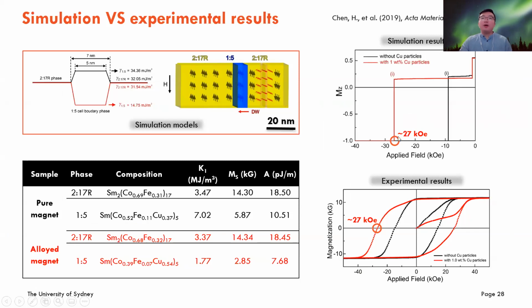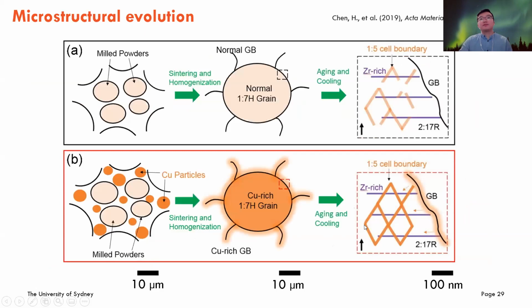For the newly copper alloyed magnets, the coercivity can reach around 27 kilo-oersted, which is almost double that of the pure one, and is quite consistent with our experimental results here, 27 kilo-oersted for the copper alloyed magnet. And then we compare the different microstructures we found. Firstly, the 1:5 cell boundary phase becomes more continuous, but also the copper actually diffuses from the grain boundaries, which serve as a diffusion path into these 1:5 cell boundary phases. Then the copper concentration becomes higher, which poses a higher pinning force for the magnetic domain motion. That's the reason for the coercivity enhancement.